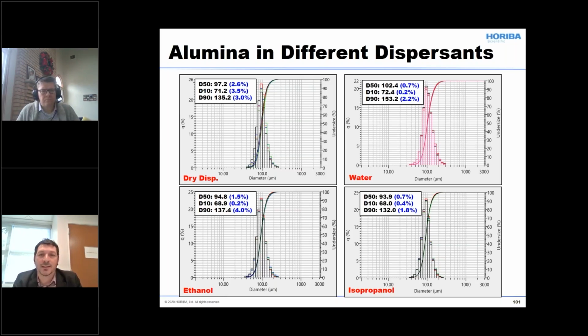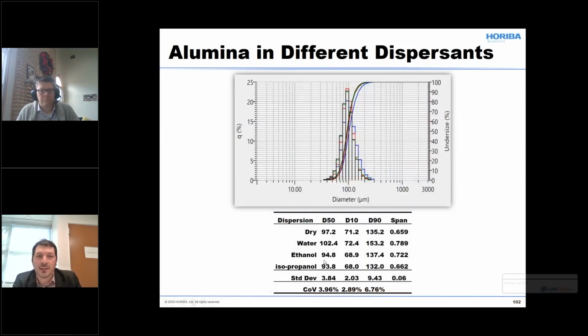And here I have a summary of this data. You can see the summary of the data in water, dry dispersion, ethanol, or IPA. It had a very low standard deviation and also very low coefficients of variance, which shows that any of those mediums would be good enough for me to disperse my particles. And of course, if I have the luxury of choosing, I can disperse well in all these mediums.